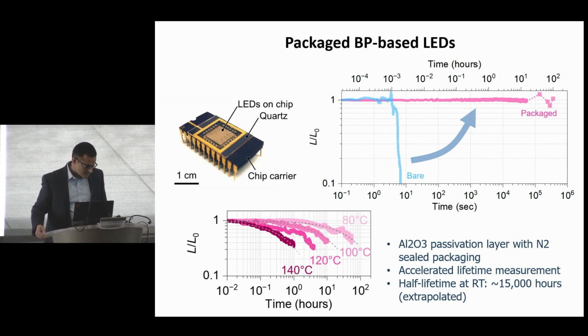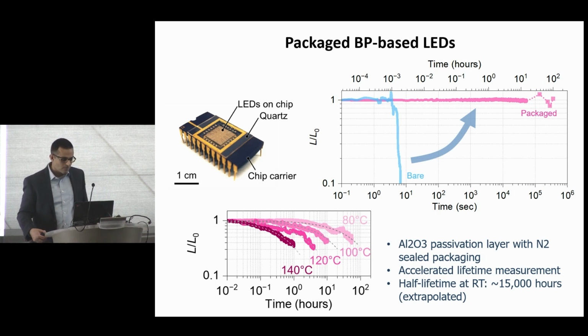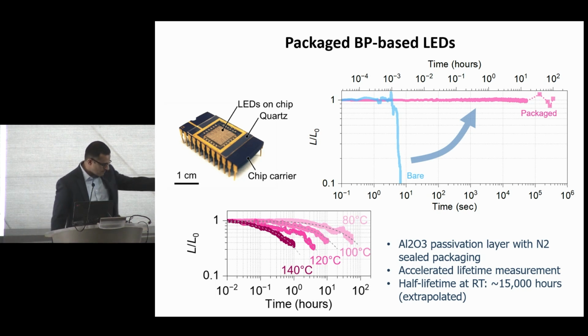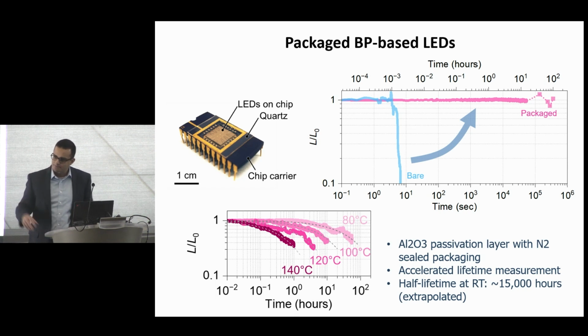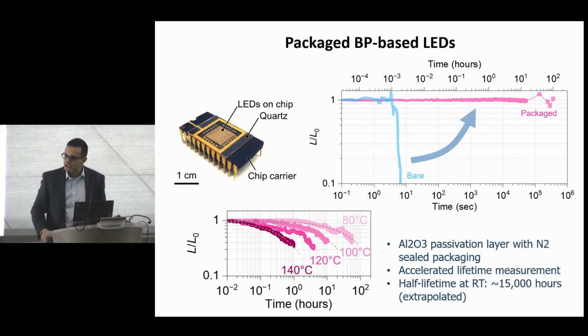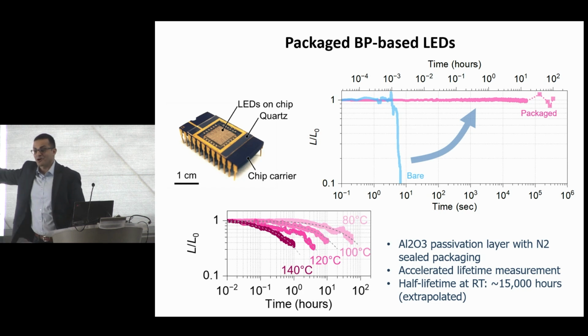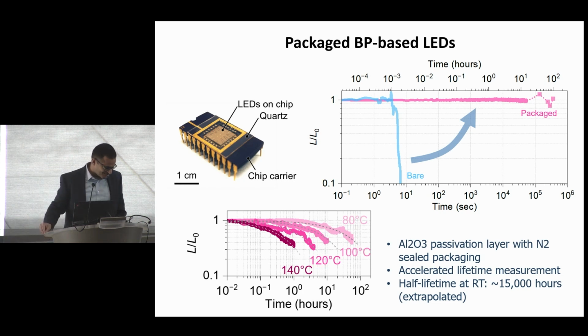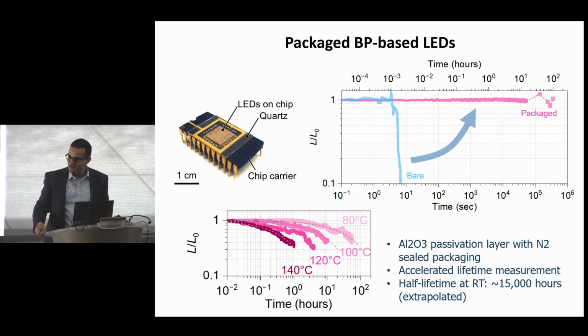And I didn't talk about the processing, but one of the processing techniques that we're using now is to make inks. So we can just grab black phosphorus, make an ink out of it, and the surface is pristine. The surface is inert, as I told you. We can just solution process the ink on the surface, and we can make very bright mid-IR LEDs, because the state-of-the-art is so poor. So it's always easy to compete in an area where the state-of-the-art is poor.